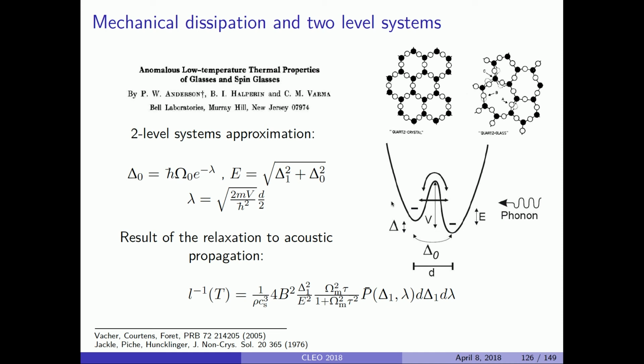And the reason it was larger is that you can think of an amorphous material as the equivalent of a crystalline material where all the unit cells have disorder. What this implies is that if you look, say, at SiO2, quartz in the crystalline form, and here quartz glass, the amorphous form, then at low temperature all these SiO2 molecules in their respective network have many equilibrium positions. And the different conformations differ by energies that are very, very low. So you have very low-lying energy excitations.